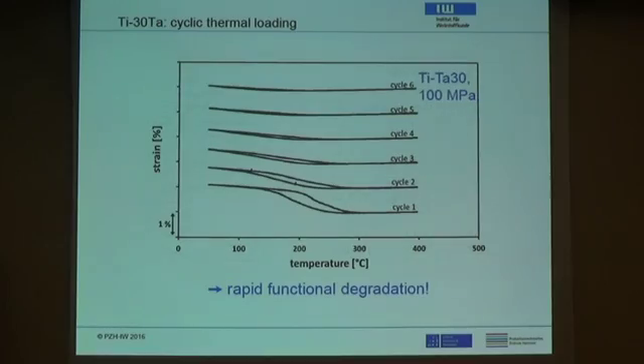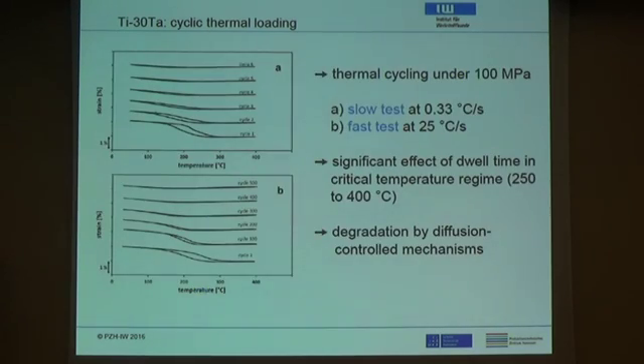The data that you see here was actually from a slow test. We changed the temperature by only 0.33 degrees C. So this is the data that we have just seen. Then we repeated this test at a much faster rate. This is roughly a factor of 100. And this is the data that we got here.